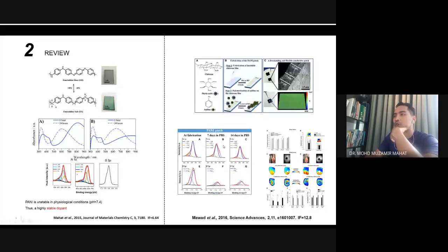To explain the top part, I'll explain this in the class for advanced characterization using XPS. But what you probably need to know here is that the stability of the film increases, as we can see that these phosphorus peaks are still available after 14 days.